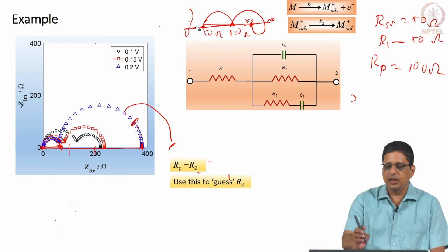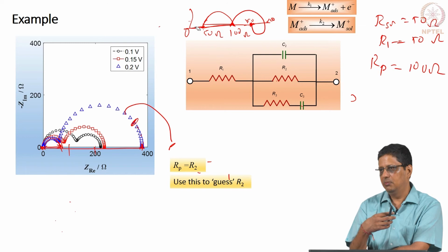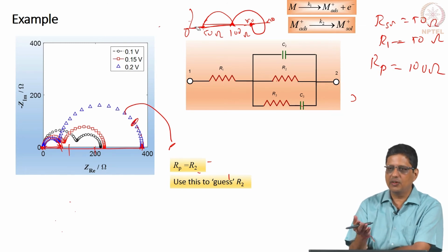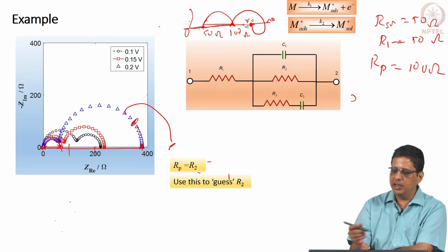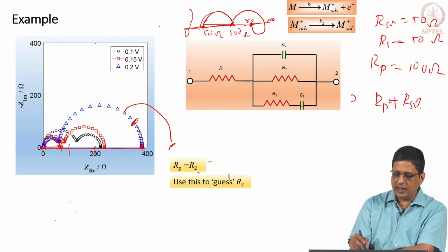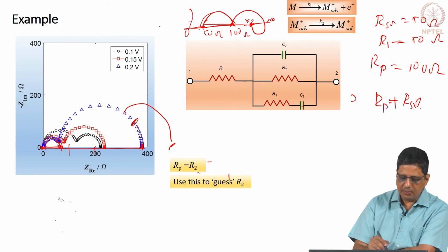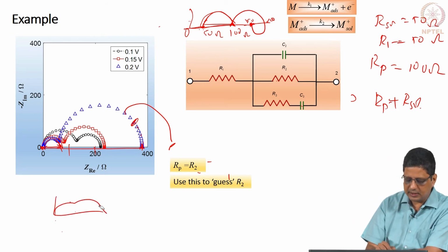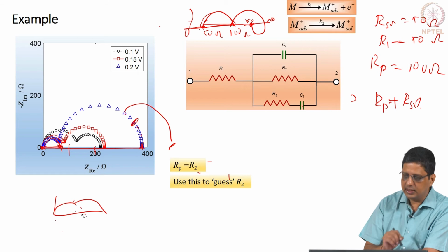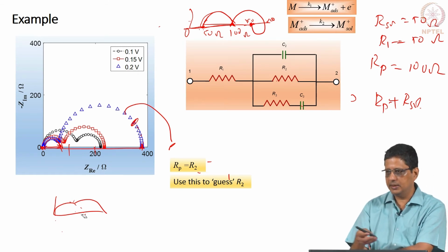and then you can estimate RT and RP very easily by looking at the actual values, but that is not such a difficult thing, you do not have to really move the spectrum. You measure the low frequency limit, and remember the low frequency limit is going to be Rp plus R solution. You estimate where the first capacitive loop is going to hit the real axis. Sometimes you may get data which goes like this, then you will have to guess it is roughly there, and then of course fit it and see where it comes. Does it make sense?